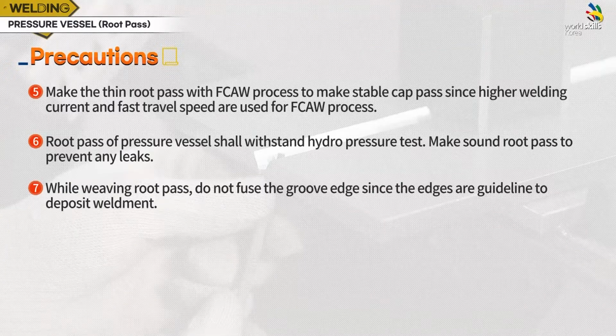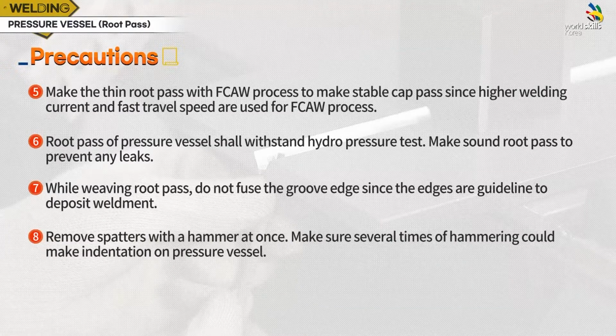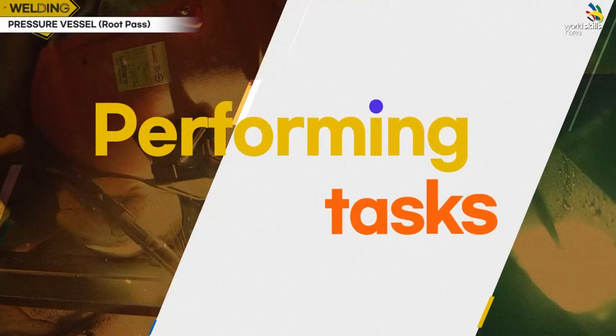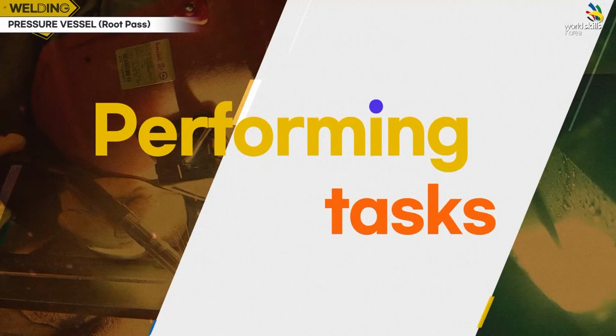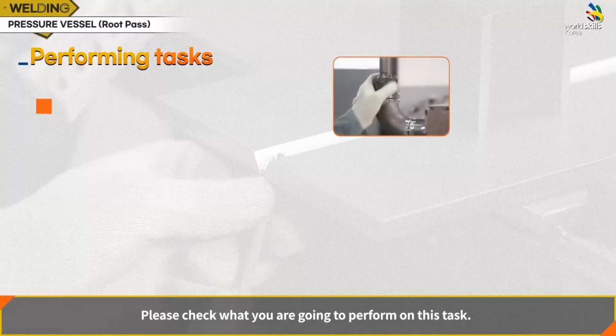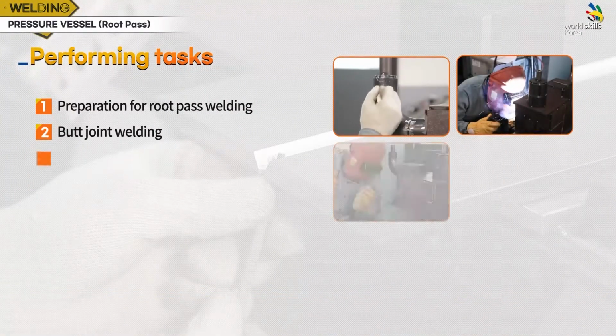When weaving during root pass welding, never touch the end of the improved surface. Be careful not to melt the edges, as the ends of the improved surface become the reference line for stacking surface beads. Remove spatters with a hammer at once. Make sure several times of hammering could make indentation on pressure vessel. Please check the tasks to perform.